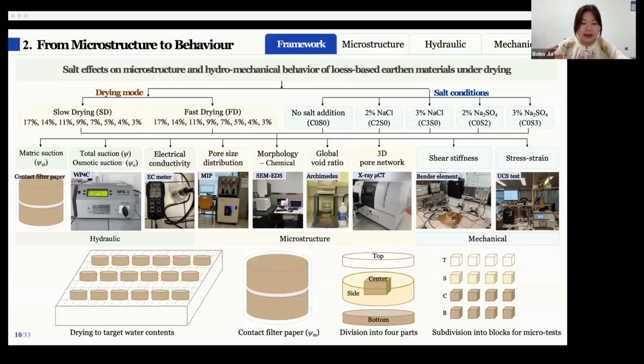So to make better use of the samples and to ensure that the micro, hydro, and mechanical data correspond to the same conditions, the test followed the procedures described below. And in addition, the triplicate samples were prepared to ensure the reliability of the data and to control the experimental variations. And at each target water content, the samples were sealed with the filter paper and placed in a controlled cooling room for at least 2 weeks to achieve equilibrium.